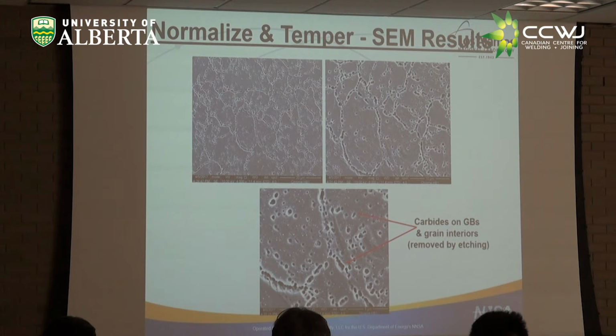Before I mention to you what happens when you etch with the etchant we used, so you see the grain boundaries here. There's little holes there. Those were where carbides used to be. They were chromium carbides. The etchant we used removed the chromium depleted region and caused the carbides to fall out. This is called ditching, basically, in corrosion terminology. So you see that there was lines of carbides along the boundaries, and then on the grain interiors, those are all gone. But believe me, they were there at one time.